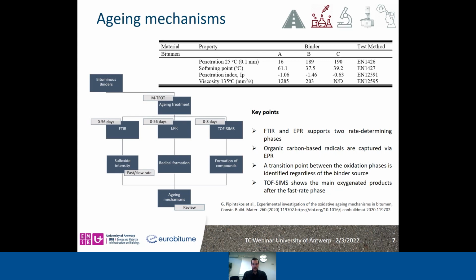For that reason, we used a kind of modified aging simulation, having thin film oven testing, but at a different temperature, at 50 degrees, in order to accelerate the process a little bit from realistic conditions. Different time intervals from 0 to 2 months were used with different spectroscopic techniques, which I will go into in detail in the next slides, with the goal, of course, to capture intermediate and final products of the hypothesis that existed until nowadays, and to review if this hypothesis and the aging mechanisms are valid or not.